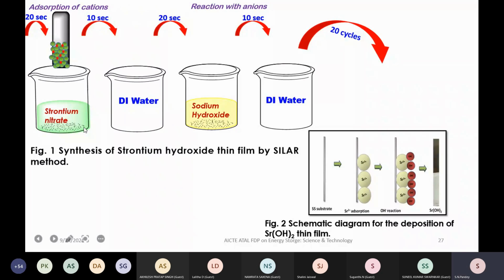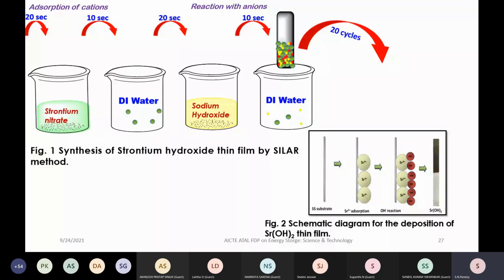one can see that the substrate is being dipped in the strontium nitrate, then some of the ions are going to be deposited here. So it is the strontium ion that has been deposited on the substrate. Then some of them will be loosely bound. Then what we do, we put it in the DI water. So if you are dipping in the DI water, then loosely bound ions or unreacted ions are going to be dissolved in the DI water. Then here we have taken the sodium hydroxide, that is, OH ion reaction will take place here, and it is going to form the strontium hydroxide. But after that, chances may be that some of them are loosely bound, so we have to put it in the DI water again. So if you are putting in the DI water, then loosely bound species will come out, and this is called one cycle. So we have to repeat it.